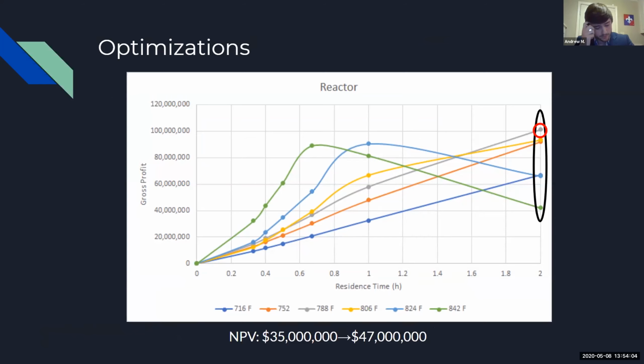And with this residence time, we were able to find the volume of the reactor that we needed, being around 76,000 standard cubic feet. And we found out that using two reactors half the size rather than one big reactor actually saved us about $10 million in capital costs, which brought our base NPV of 35 million up to 47 million.